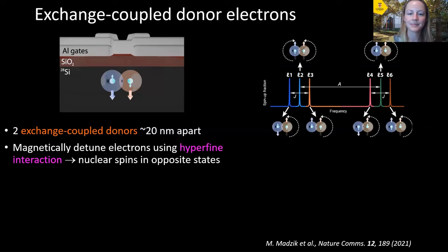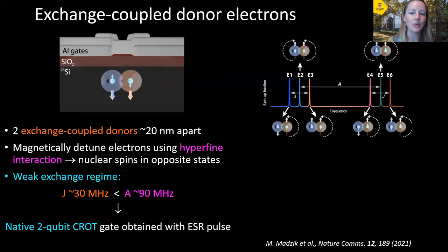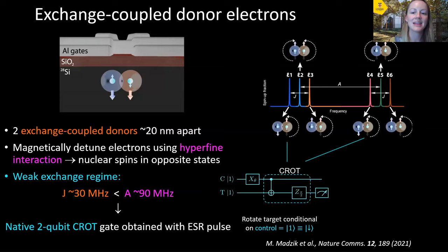And in this device, we're in the weak exchange regime, which means that the exchange interaction is much weaker than the hyperfine couplings. And in this regime, we would implement a native C-Rot gate that can be obtained with just a single electron spin resonance pulse on resonance with one of these transitions. So for the 2 electron spin resonance transitions shown in blue here, this is an example of a C-Rot gate because it rotates the target electron in brown, conditional on the control electron in blue being in the 1 state or the spin down state.